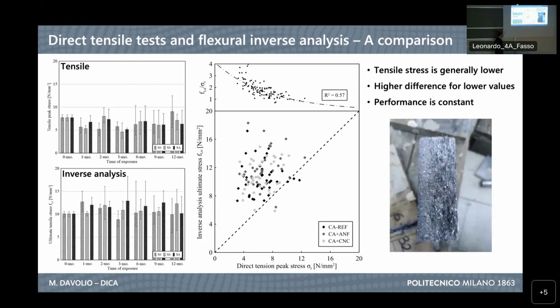But what we discussed about this was that the tensile test had two different problems, which on one side is the distribution of the cracks. You can see from this picture of the section that cracks are mainly distributed on the bottom of the slab. Thus meaning that if we test it under flexural loadings, it is very effective in acting as a tensile reinforcement. But when all the section is under tensile stresses, we experience failure from the side where we had poor content of fibers. And the other issue related to the tensile test is the permanent deflection we had on the specimen, specifically after 9 or 12 months, which then causes it to fail not under pure tensile, but under flexural and tensile stress. And for this reason, we had lower values of stress.